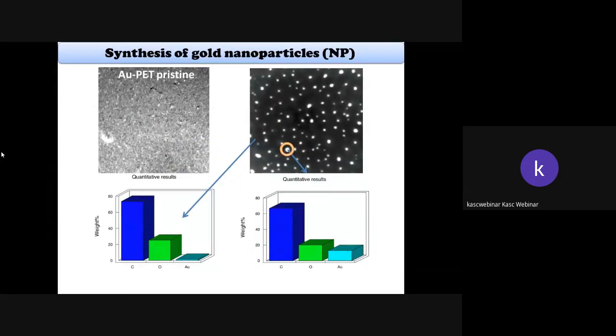Actually, when the PET pristine sample is subjected to ion beam irradiation, especially argon ion irradiation, the pristine sample shows a uniform morphology through the SEM analysis, and the second one clearly indicates a possible bright spot over the irradiated one. Then we can identify what the bright spot is after irradiation. These bright parts represent, in elemental composition, a greater amount of Au when compared with the dark spots. So this clearly indicates the formation of different size nanoparticles, or gold nanoparticles, decorated over a PET substrate.